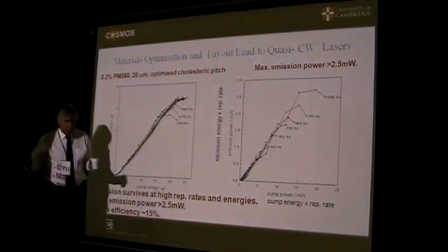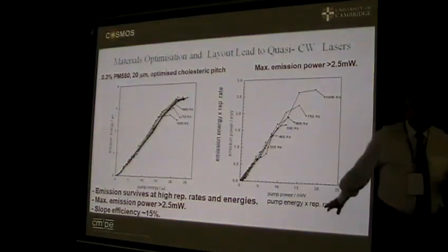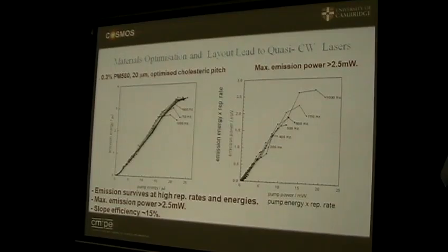The measurements we've done are stable at that repetition rate in the lab for many months. A liquid crystal cell just made, sealed in the normal way with edge seals. We're doing lifetime trials now, but that's months, and it'll stay stable for months.